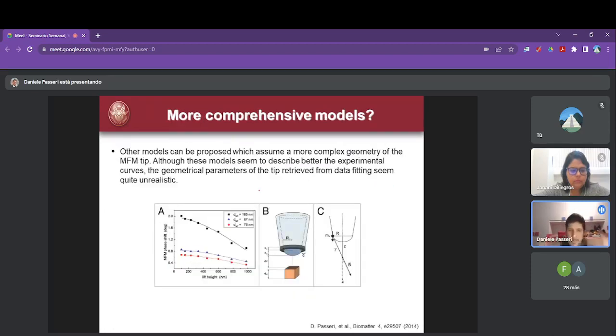Of course, the first thing you do is create more comprehensive models. For instance, we started thinking about the fact that the tip was without the magnetic coating, so there was just a ring, and so on. We could fit the results, but when you have many free parameters, you can fit almost everything. The problem is that the geometrical parameters, like the radius of the tip, were quite unrealistic. We obtained a radius of 10 microns, while the tip was expected to be 50 to 100 nanometers. So that was not a good approach.